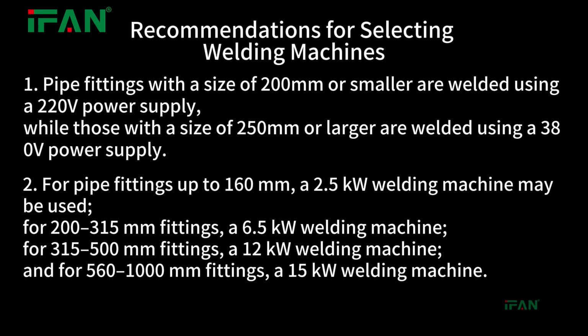1. Pipe fittings with a size of 200 mm or smaller are welded using a 220 volts power supply, while those with a size of 250 mm or larger are welded using a 380 volts power supply. 2. For pipe fittings up to 160 mm, a 2.5 kilowatts welding machine may be used. For 200-315 mm fittings, a 6.5 kilowatts welding machine. For 315-500 mm fittings, a 12 kilowatts welding machine. And for 560-1000 mm fittings, a 15 kilowatts welding machine.